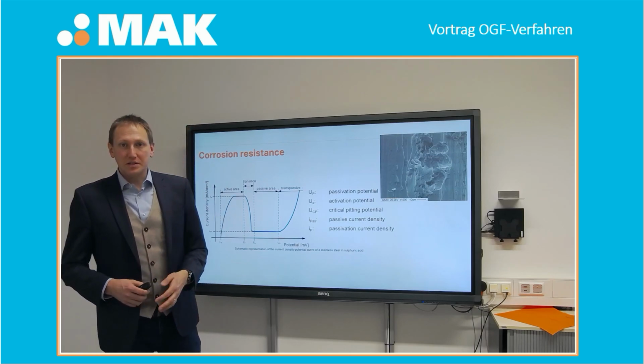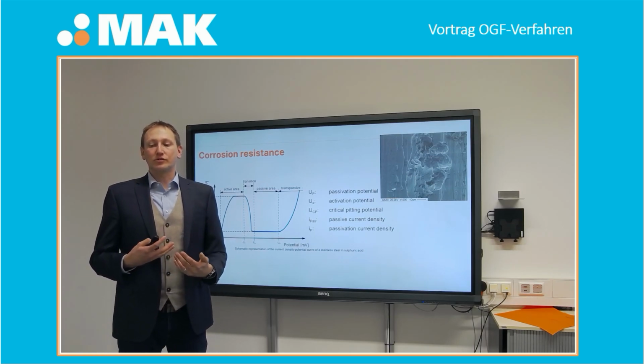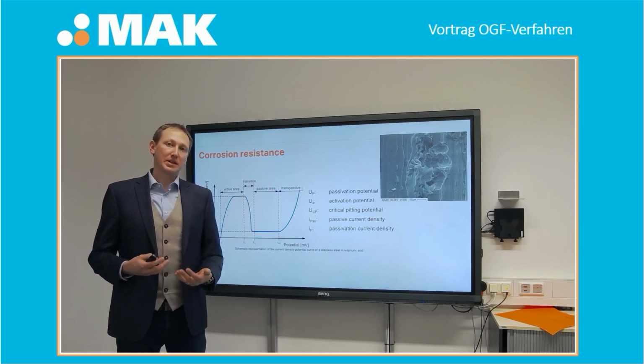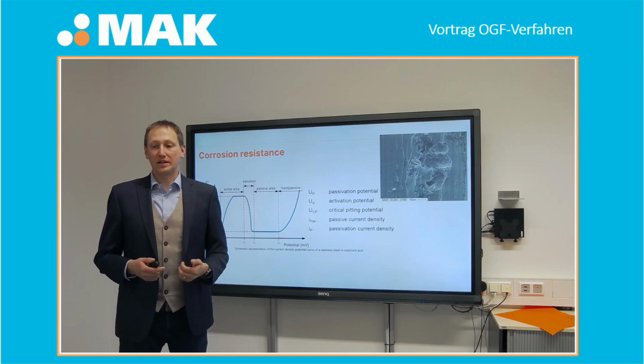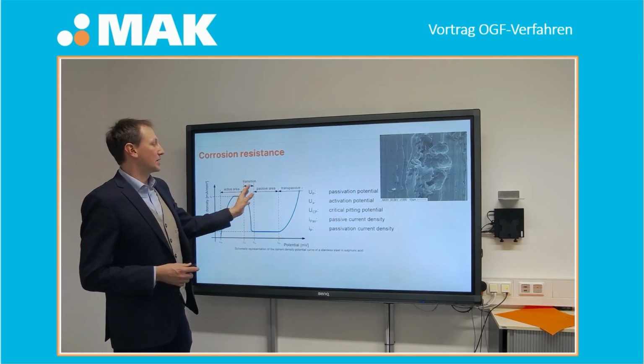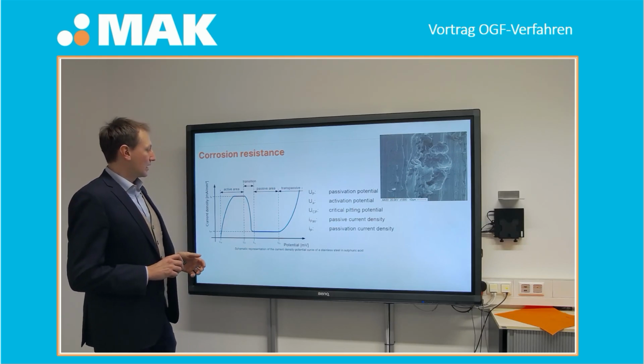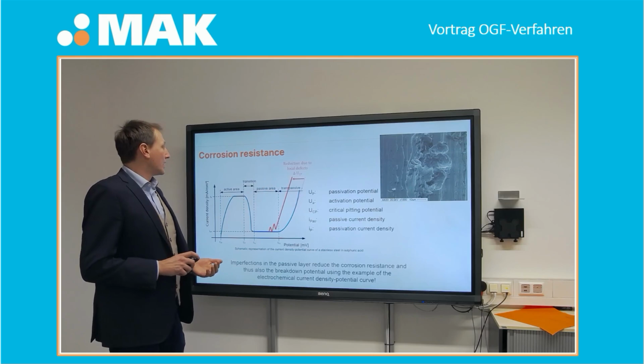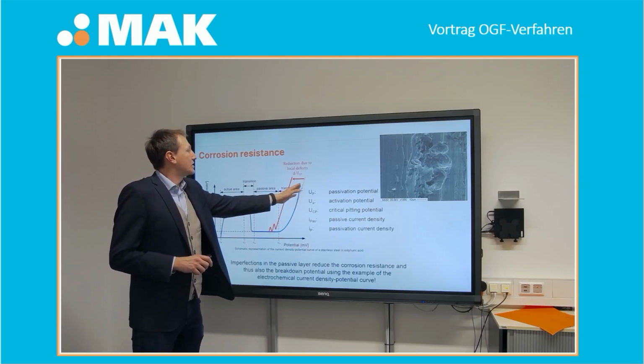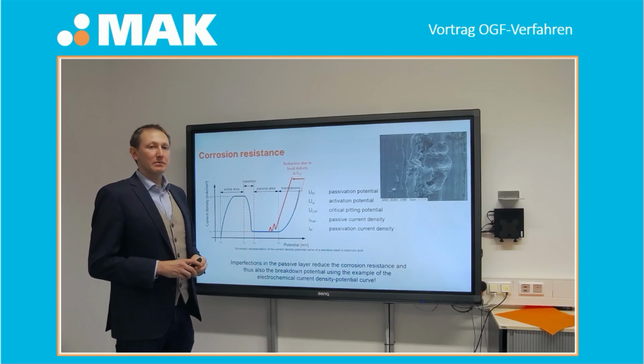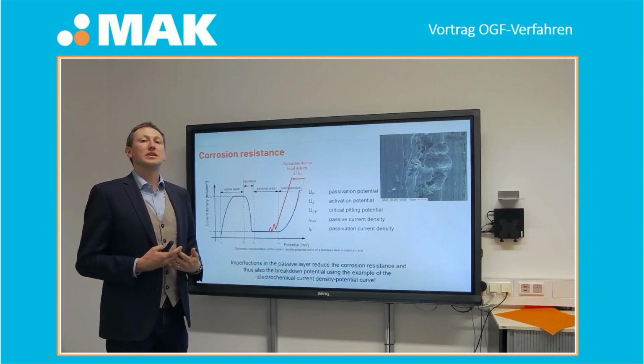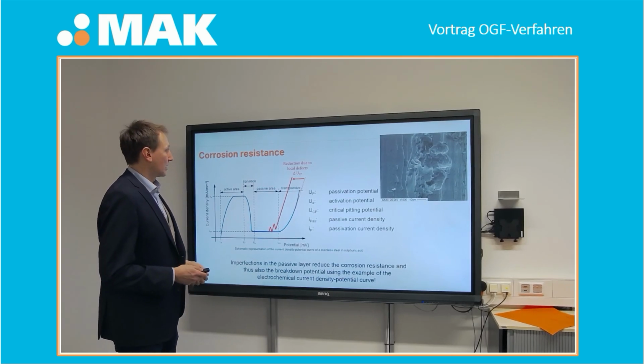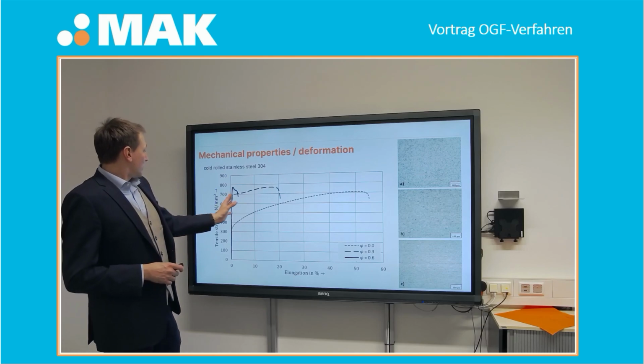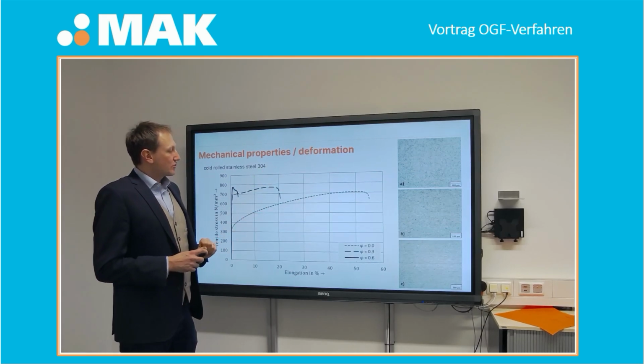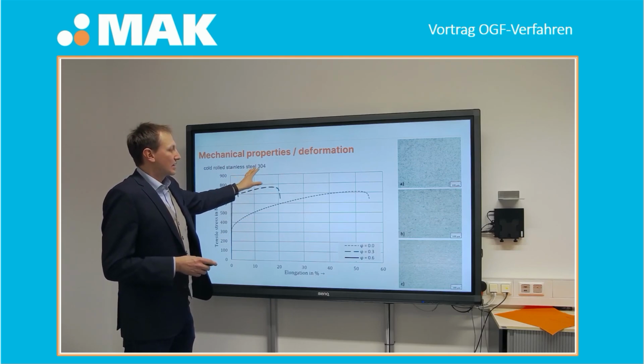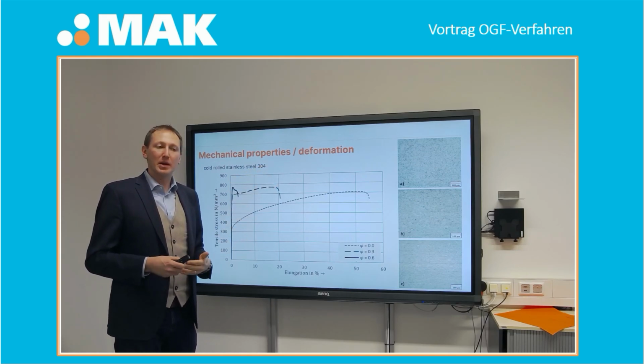Talking about corrosion resistance, for stainless steel we are mostly talking about critical pitting temperature or critical pitting potential. In this case, we carried out some tests by the critical pitting potential, according to the ASTM standard. And by local defects, you have a decrease of the critical pitting potential, which means your surface is weaker against corrosion.